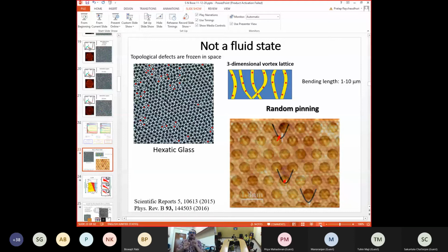Now these vortices, when I drew a cartoon, I drew them as straight lines like this, but they need not be straight lines. They are more like spaghettis, and they can bend, they can even intertwine with each other sometimes. From the elasticity, you can calculate what would be the typical bending length at a temperature. At this temperature, the bending length would be something like 1 to 10 micron. So if you have to consider something as really two-dimensional, you need to be at a thickness which is much smaller than this bending length.